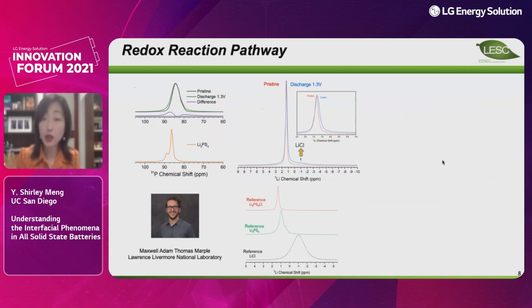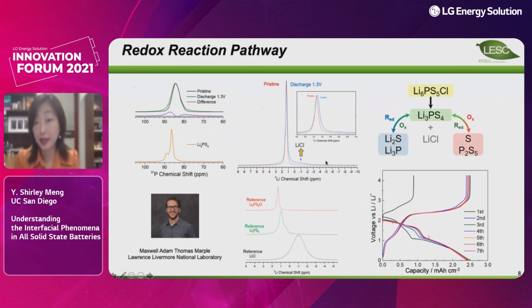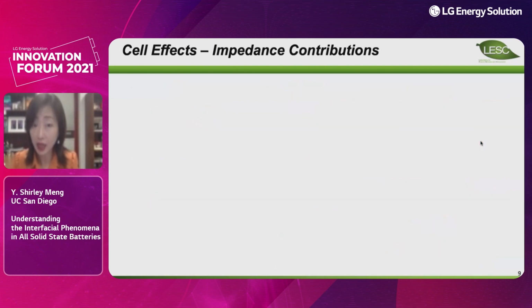The redox reaction pathways have also been confirmed by our NMR expert from Lawrence Livermore National Lab, Dr. Thomas Marple. NMR is a very promising technique. With this group of techniques, we were able to confirm that in the redox reactions of the argyrodite electrolyte, on the negative electrode side you form Li2S, lithium chloride, and lithium phosphide. On the positive electrode side, you form P2S5 or sulfur components. This is very critical for us to later engineer these cells so that instead of fighting against the redox reactions, we can utilize and stabilize the argyrodite electrolyte.